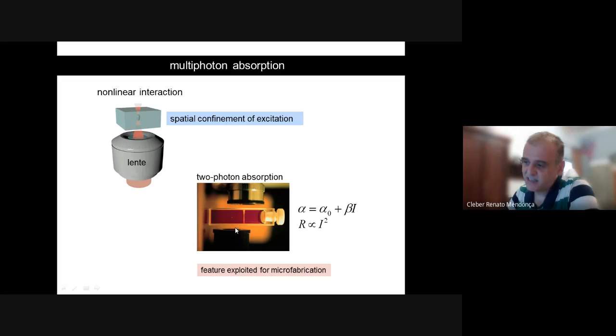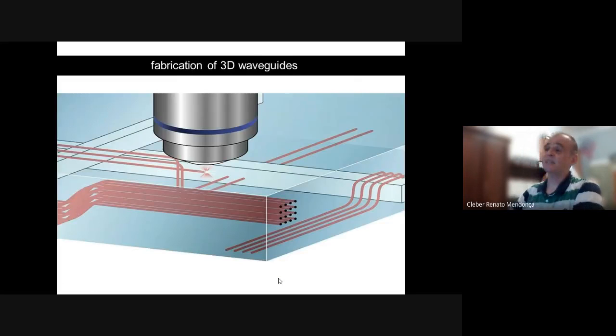But here, this laser is focused at this point. So as you can see, only at the focal point will the intensity be high enough to induce the multi-photon absorption and then excite the molecule, which will then present its emission. So as you see, the laser beam, of course, is passing from here to there, but the intensity is not high enough. Only at the focal point is the intensity high enough. So you see the localization of the excitation, and that's something that we use for microfabrication.